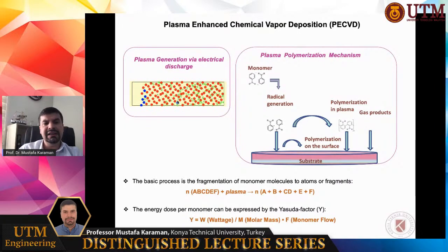Here you can see the plasma discharge, plasma generation via electrical discharge. The radicals are generated from the monomers themselves inside the highly energetic plasma zone. Once such radicals are generated, they diffuse to the surface and they polymerize on the substrate surface. So here, the monomers are dissociated into radicals. The monomer fragmentation here is unavoidable, which is actually not good in terms of polymer functionality.